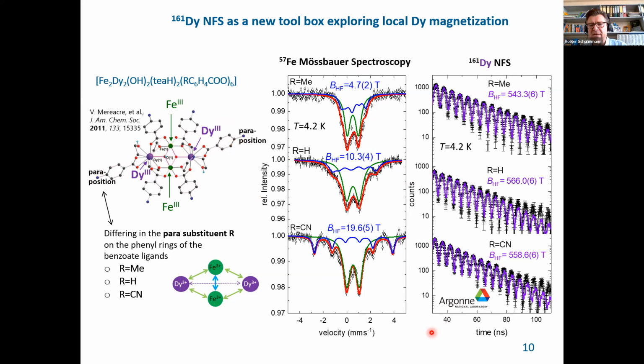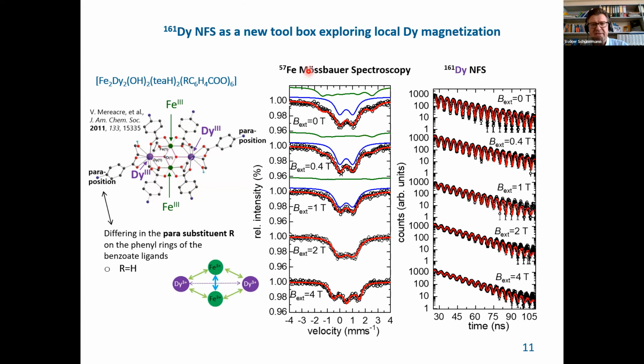And we were interested whether we could also see some impact in the dysprosium NFS. And in fact, we see quite a high impact, 543.3 Tesla for the methyl, and 566.0 for the hydrogen, 558.6 for the cyano. It's not in line with the change in hyperfine field of the iron here, but still it's an influence.